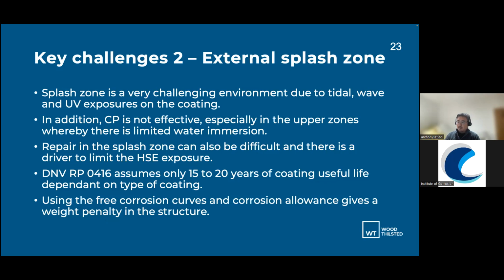These structures, as I say, there are only between 50 to 100 structures in the ground. So you want to try to limit the amount of time you have to go to each and every single one of them. The challenge that we face is that from a coating life point of view, the coating useful life that we could take in the design is between 15 to 20 years. And after that, we have to use a free corrosion curve and a corrosion allowance, which means we get a massive penalty cost in terms of weight.